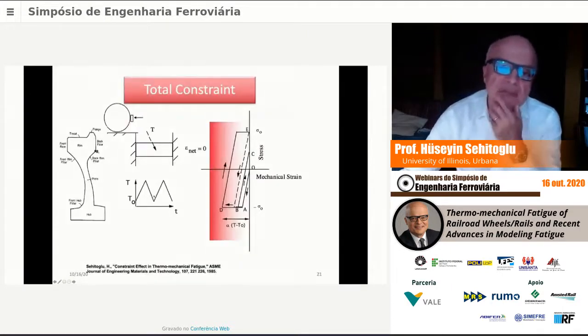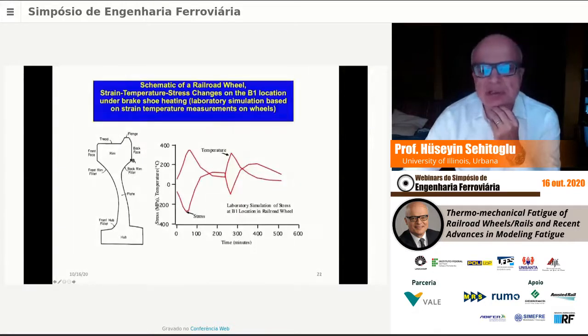Now, if we look at some experimental work, it's trying to simulate the temperatures and strains in this B1 location. This B1 location is more or less a uniaxial state of stress, so it's possible to measure the temperature there. And if we impose that temperature cycle, and we can make a strain measurement there as well, and impose the temperature and strain on a laboratory sample, upon heating you go into compression. Upon cooling, you go into tension. Then in the second cycle, heating, and then cooling again.